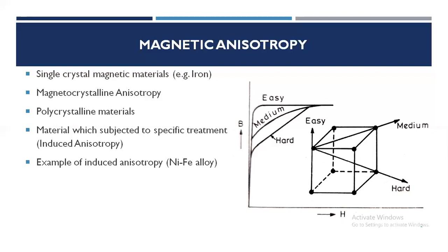A thin film of nickel ferrum alloy is deposited on a substrate by evaporation in vacuum, with a magnetic field applied in the plane of the substrate, and subsequently has its easy direction for spontaneous magnetization along the original field direction. This is another example of induced anisotropy, and thin magnetic films are used as storage elements in computers.